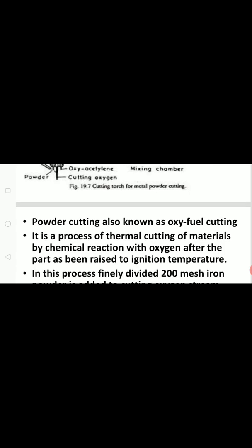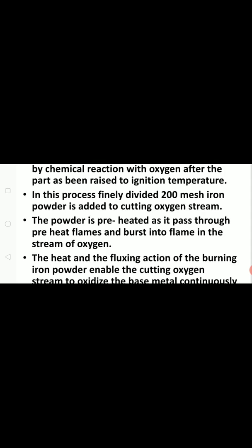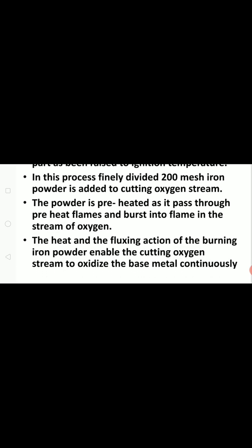Powder cutting is also known as oxy-fuel cutting. It is a process of thermal cutting of metals by chemical reaction with oxygen after the part has been raised to ignition temperature. In this process, a finely divided 200 mesh iron powder is added to the cutting oxygen stream. The powder is preheated as it passes through the preheat flames and bursts into the flame in the stream of oxygen. The heat and fluxing action of the burning iron powder enable the cutting oxygen stream to oxidize the base metal continuously.